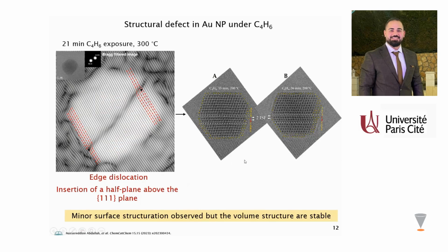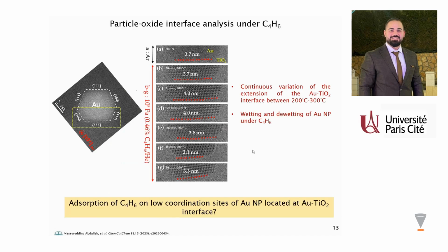So we can say that even if the adsorption of butadiene cannot induce a complete structural transition of the particle, it can highly affect the surface structuration. Finally, by monitoring the particle-oxide interface during exposure to butadiene, we saw a continuous variation of the extension of the gold-TiO₂ interface between 300 and 200 degrees Celsius, which indicates a wetting and dewetting of the gold nanoparticle under butadiene. This phenomenon can also indicate that butadiene adsorption can be located on low coordination sites of the gold nanoparticle at the interface between the gold particle and the TiO₂ support.